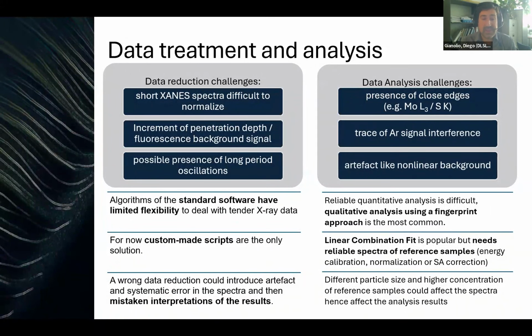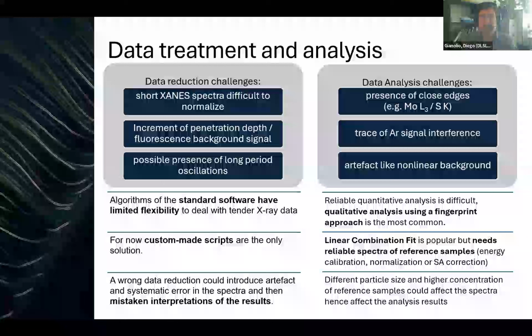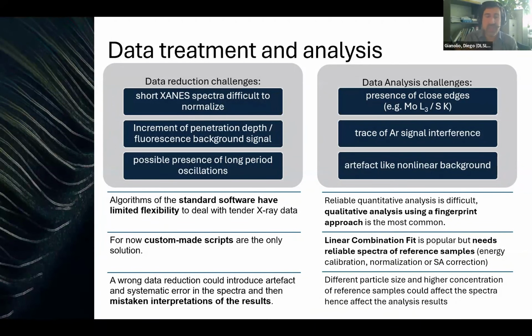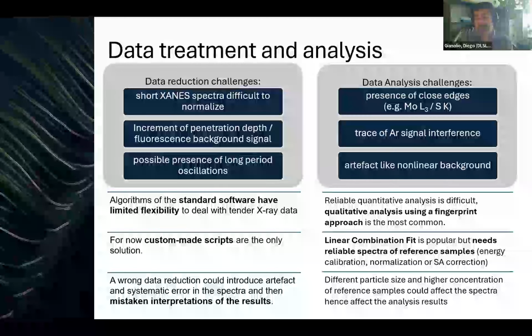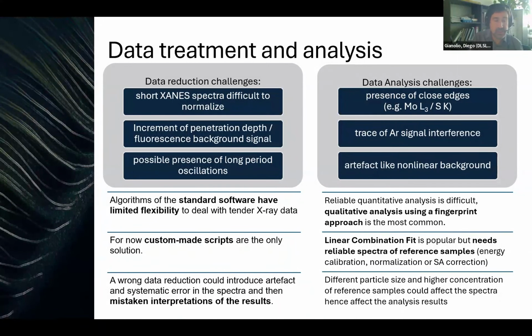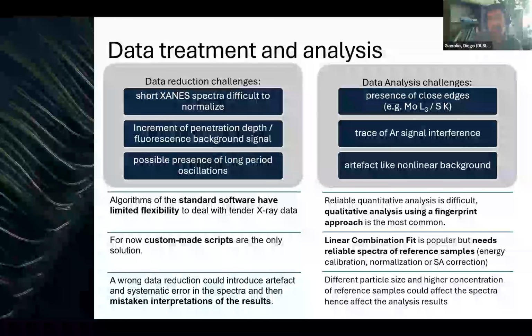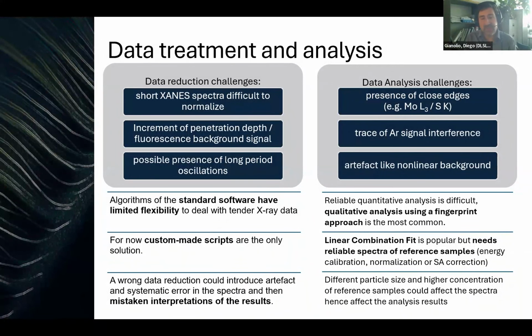So it is very hard to have a reliable quantitative analysis, and most commonly people use a qualitative analysis using a fingerprint approach. But this is still problematic because we really need to have some reliable spectra of reference samples where you don't only have the shape of the spectrum, but you are sure that the energy calibration has been applied properly, that the data have been normalized, and that there is no issue, for example, due to the self-absorption that could affect the intensity of the signal. And then we still need to be aware that samples that have different particle sizes or different concentrations, even if they are the same reference sample, could have different spectra. And so this could affect the results of the analysis.